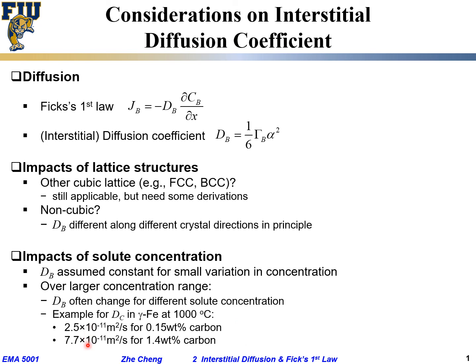On the other hand, quite often within an order of magnitude they are still roughly the same. The diffusion coefficient measurement is not that accurate. You cannot do 1.1 versus 1.2. Quite often it's between 1 versus 10 versus 100. Whether it changes depends on how precise you want to be and how critical you are concerned with your actual situation.